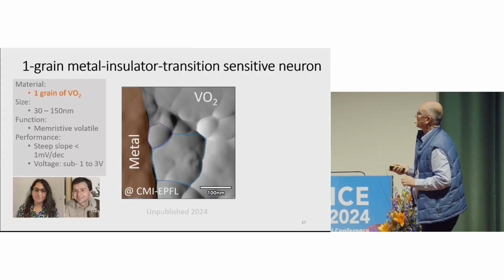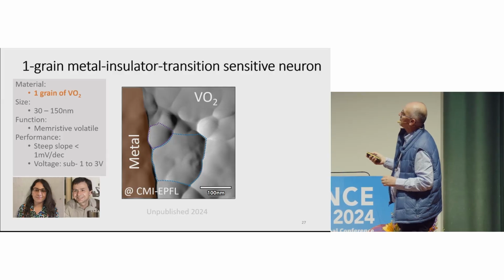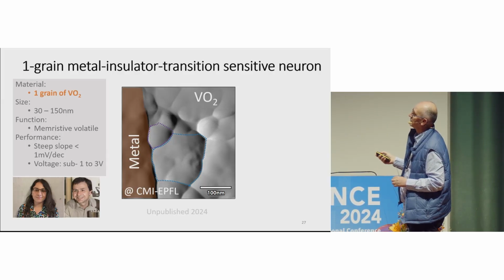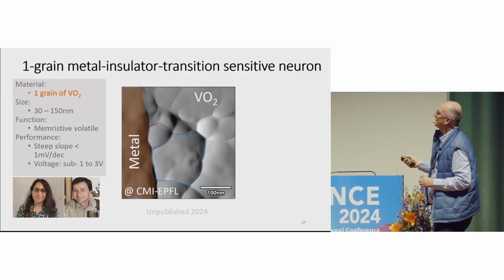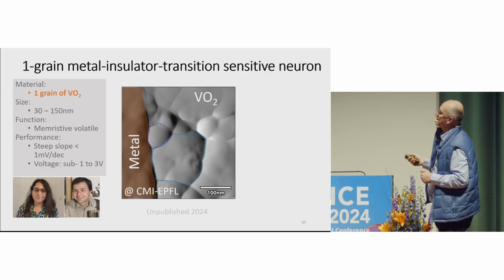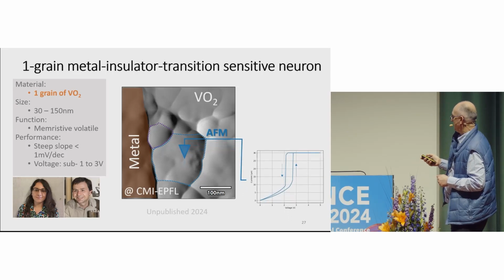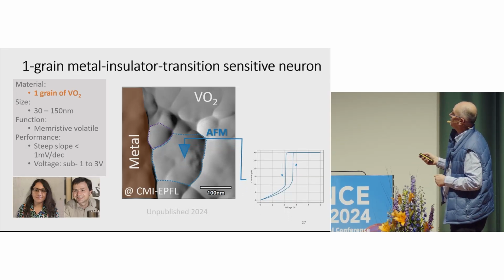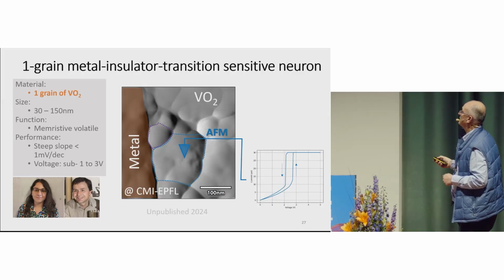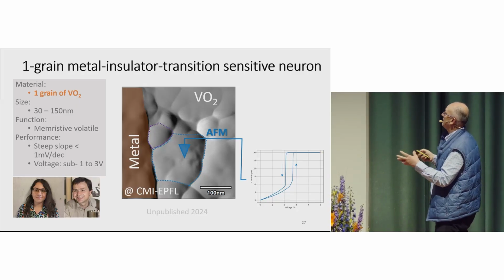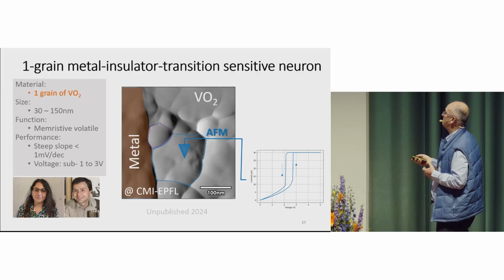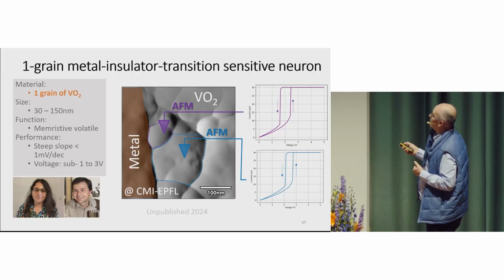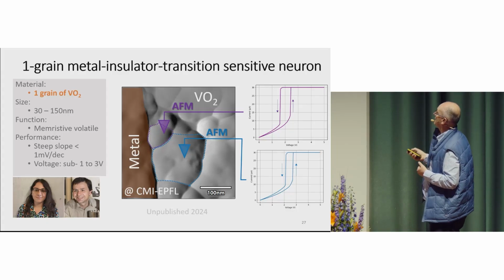So what we try to do is to make a metallization and test with an AFM the switching of a single grain of VO2. So these are 2 grains of VO2 that we reasonably suppose are crystalline, each of them. Both show transition, and what we do, we come with an AFM probe, and with this AFM probe, we test the switching of this grain between this metal contact and the AFM probe. So this property is fundamental to the material, right? It's not coming from any interaction. There are effects of grain-to-grain interaction, grain boundary, but as a crystalline state, the VO2 has this property, and this is what you get on the next grain, right? A smaller voltage, the grain is smaller, so then it explains why this has reduced hysteresis and this is larger.